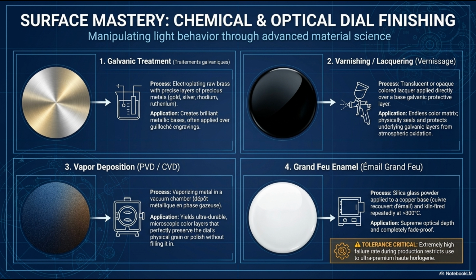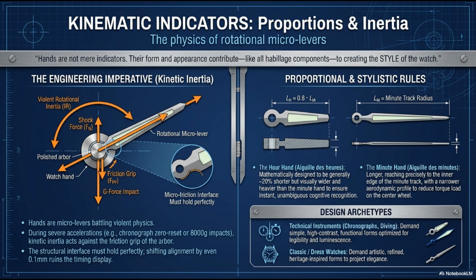Finally, Method 4 is the legendary Grand Feu enamel. Silica glass powder is meticulously applied to a raw copper base and kiln-fired repeatedly at temperatures exceeding 800 degrees Celsius. It offers supreme, unmatched optical depth and is completely fade-proof for centuries. However, read the tolerance critical warning. The failure rate, cracking, bubbling, or warping during production is extremely high, restricting this purely artisanal method to ultra-premium haute horlogerie. We move from the stationary dial to the dynamic indicators.